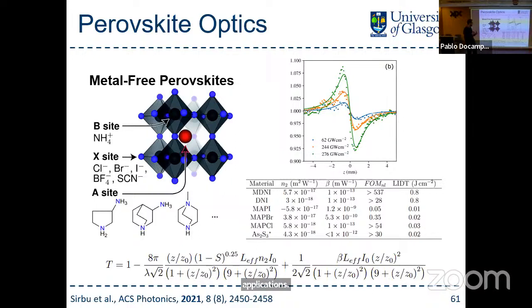The figure of merit, which is normally what you would compare them with, is actually quite good for these types of materials, and it's about 10 times better than you would get for silicon, for instance. So if you're looking at a semiconductor platform for optics, these are not bad options. Bandgap is wide, so that means they're actually quite stable. And we can grow them in fibers.